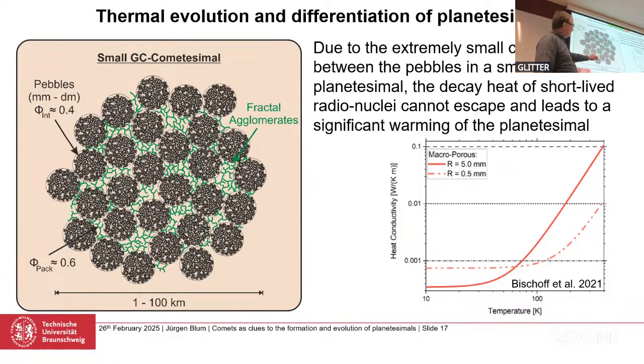The point is here, this is a pebble. So the pebble consists of micron dust particles with a very low heat conductivity itself. But here we have a planetesimal consisting of intact pebbles, because we're talking about small planetesimals. And the heat transfer from one pebble to the other is very, very minor. So extremely small. We are talking about values of the order of less than 10 to the minus 3 watts per meter and Kelvin. If you're familiar with heat conductivity, a typical material has values between 1 and 10. So we're down by 4 orders of magnitude. So there's absolutely no heat to be transported here.